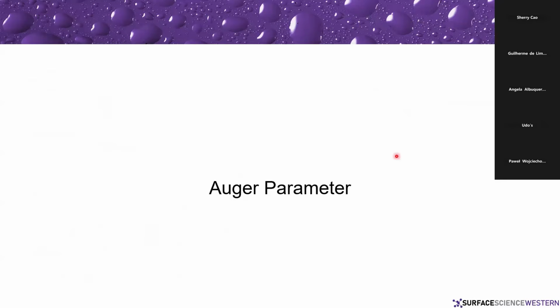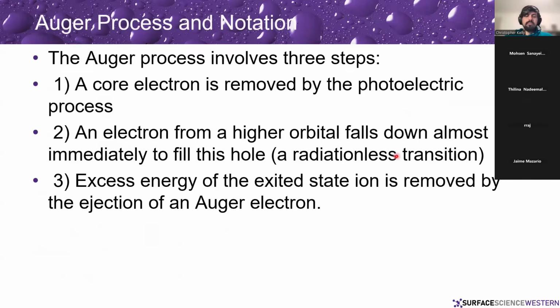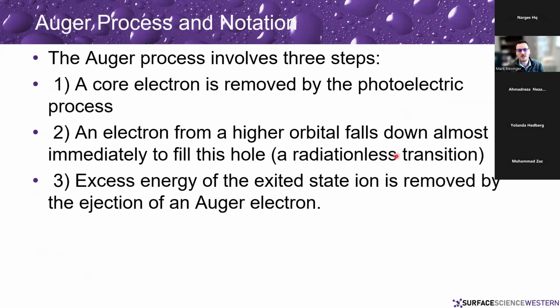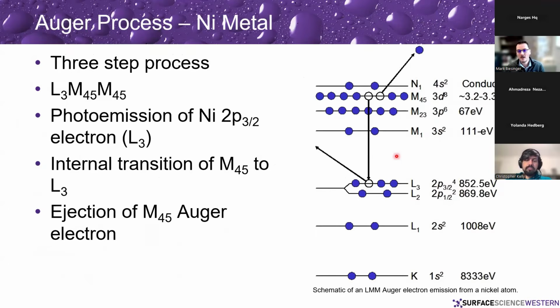How are we for the Auger parameter? The Auger process involves 3 steps. So you kick out a core photoelectron. You're using the photoelectric process. An electron from a higher orbital falls down almost immediately to fill that hole, and then the excess energy of the excited state is removed by the ejection of an Auger electron. So again, you kick off a photoelectron, an electron drops down, and another electron gets kicked out. So it's a 3-step process to produce an Auger electron.